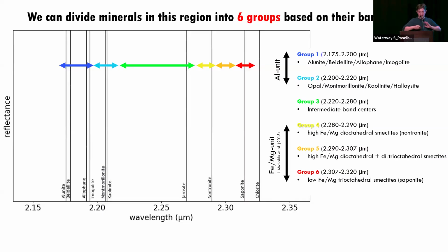We can actually subdivide this region of the infrared then into like 6 or so groups based on band center. So for example, in cyan, between like 2.2 and 2.22 micron band centers, we find montmorillonite, kaolinite, and halloysite, which are minerals of particular interest in CCS, but there's a whole bunch of other groups we can get. And actually, for these final three, I took the band center bins straight from Michalski et al. 2018, which studied in detail the iron clay, magnesium clay, and the intermixing that goes on there.